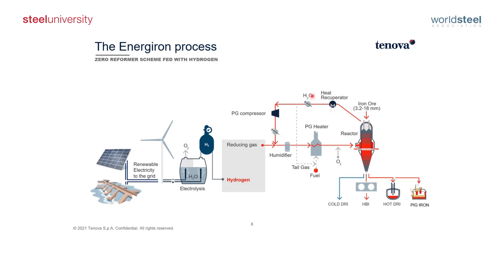Then the gas that has been cleaned by steam, so the steam is condensed, then the carbon dioxide, the CO2, and then hydrogen sulfide are stripped away via amines, and then the cleaned gas is recirculated inside the module, reheated in the process gas heater, and then back in the module, added with fresh gas, either hydrogen or natural gas or coke oven gas or any similar gas suitable for the DRI operation.